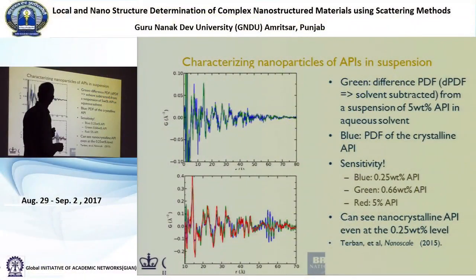Then what we wanted to do is look at the drug in suspension. So we start then looking at lower and lower concentrations. So the green curve, it says that the blue is the PDF of the crystalline API, and the green is 5 weight percent. But it looks like it may be the other way around. But the point is that there's a bit more noise now, but the green and the blue curve, you can still see the signal there. So even at 5 weight percent of API in aqueous solvent,